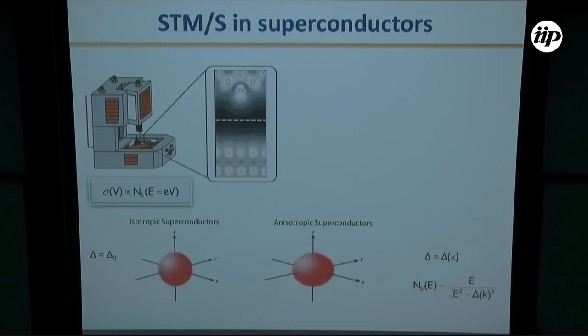Well, one important point that I want to stress, and I will use later in the talk, is that in an STM, the Z-axis transport is not the only contribution to the tunneling current. Due to the small lateral size of the tip, quasi-particles are injected in all directions. So all the parts of the Fermi surface contribute to the tunneling current with a significant weight.